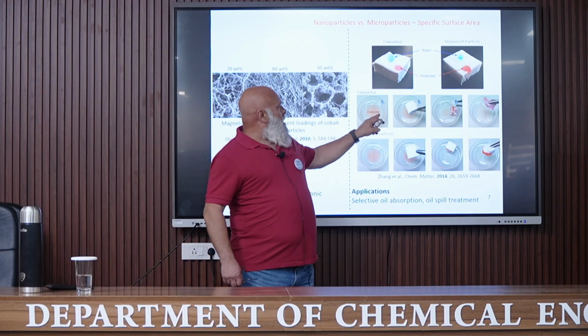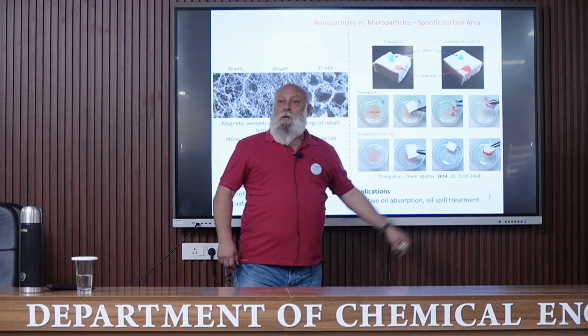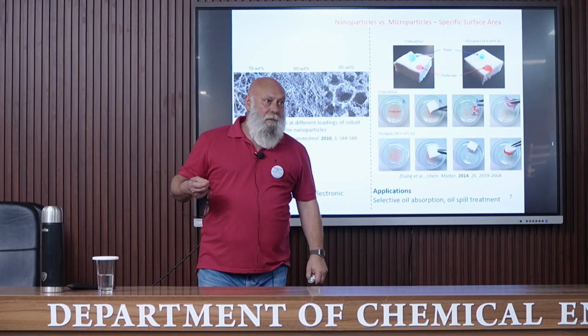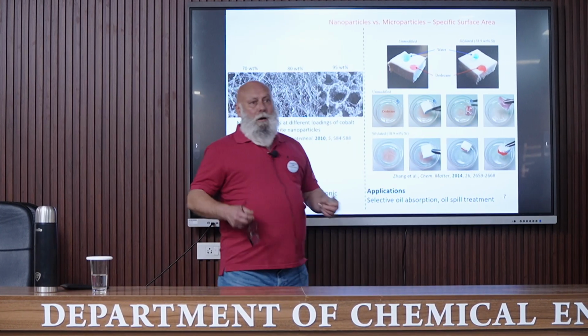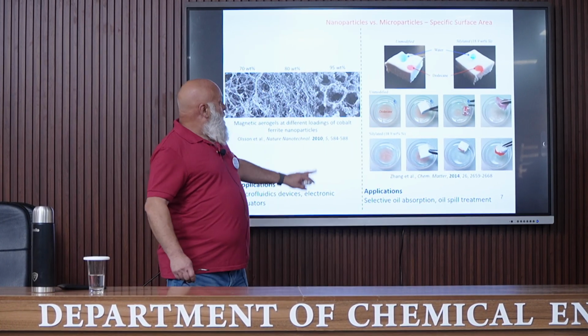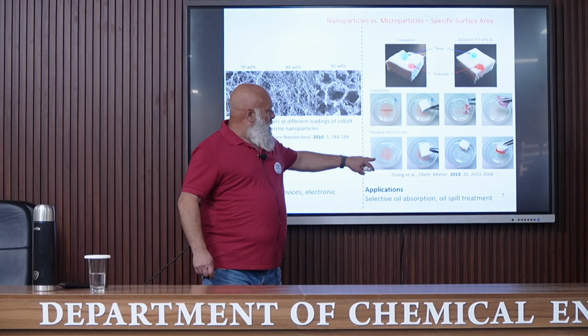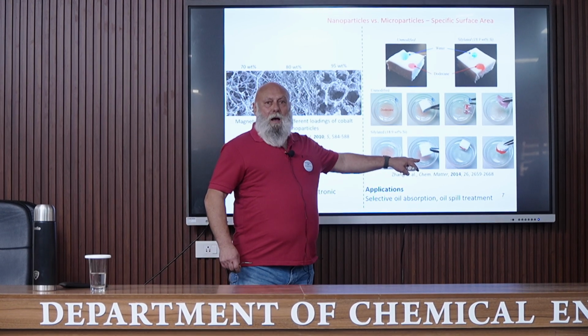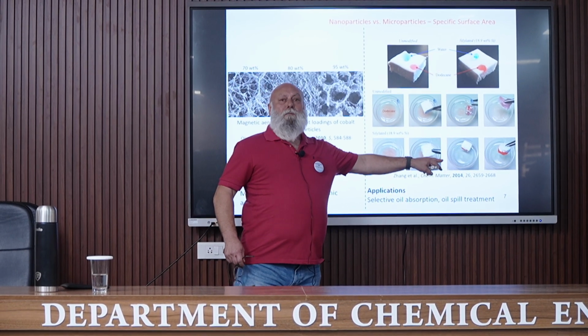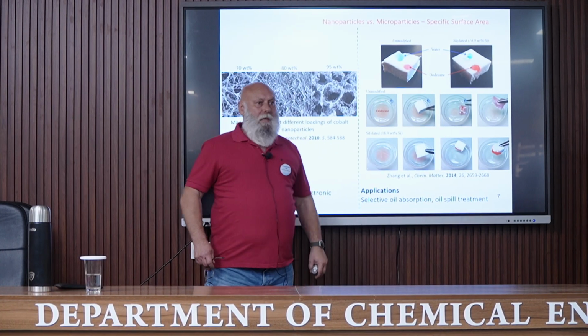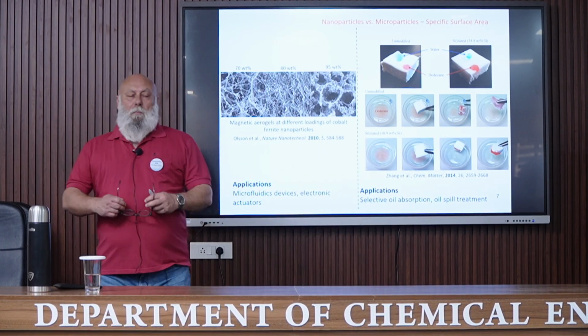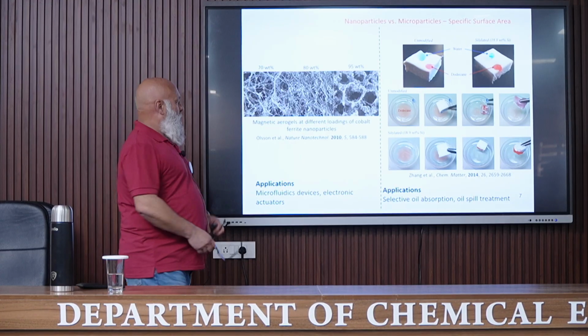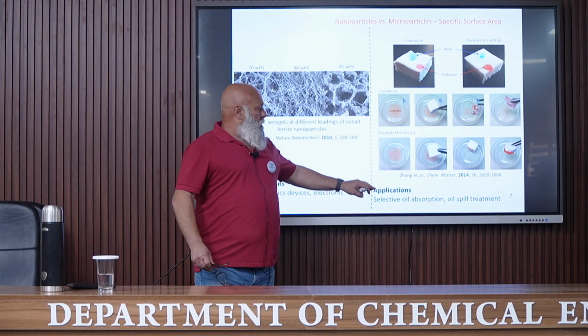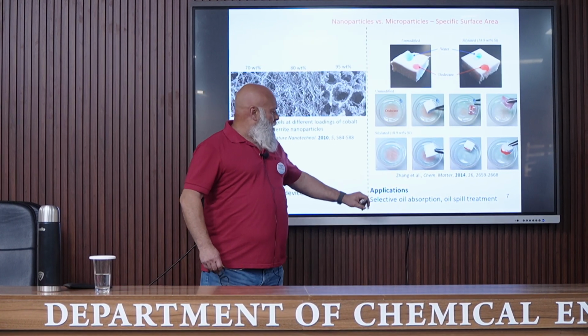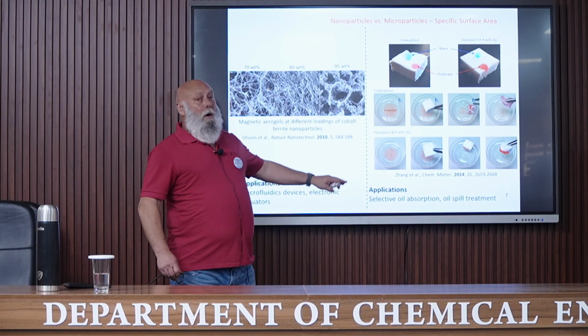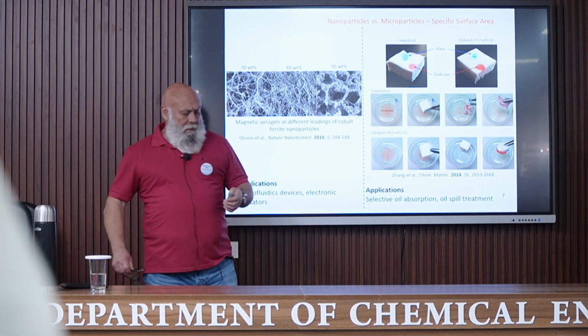For the unmodified sample, both liquids are absorbed, and you can see that the aerogel lost its form. In the case of the modified aerogel, we have a selective absorption of the oil phase. And you can see that the material keeps its form, meaning that it can be reused. And of course, possible resulting applications are for selective oil absorption or also for oil spill treatment.